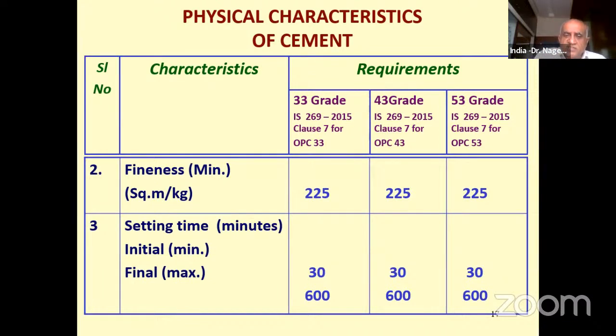Setting time of cement is a test which is used to accept or reject cement. Whereas setting time of concrete is done only when you are using a chemical admixture, to check whether the concrete setting is affected because of the presence of admixture. So the concrete setting time procedure is different. Cement setting time test procedure is different. Cement setting time test is only for the quality control checking of the cement, whereas there is a setting time test for concrete also, which is only to check the effect of chemical admixtures on the concrete.